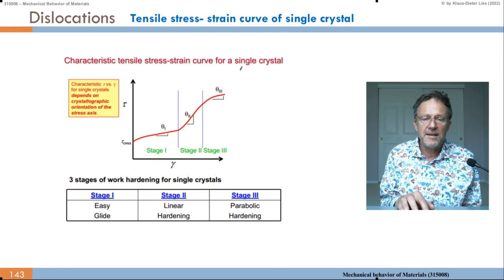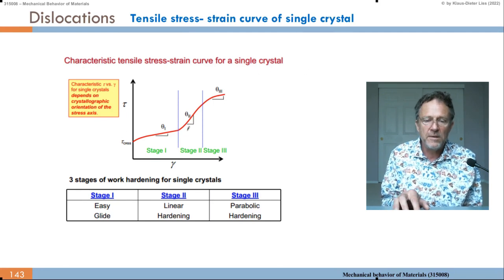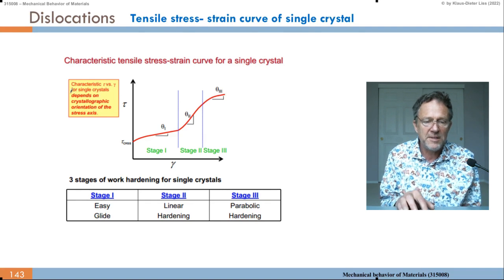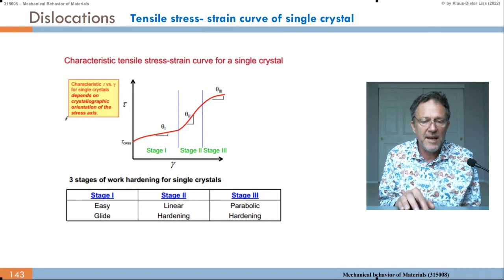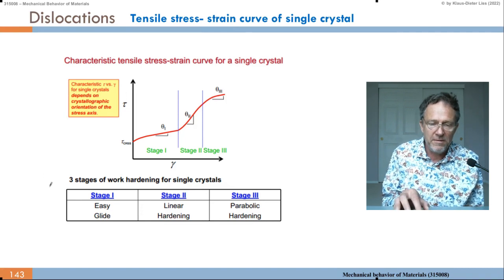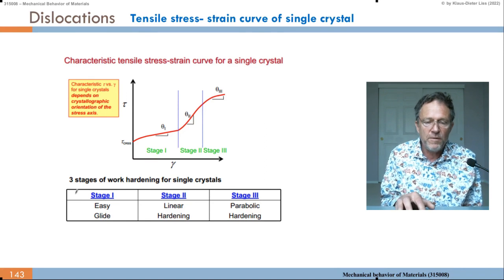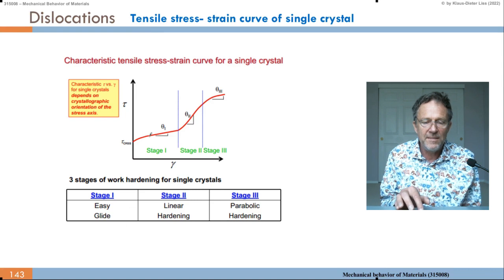So this is a characteristic tensile stress-strain curve for a single crystal. We have stage 1, then stage 2 with a larger slope, and stage 3 with a smaller slope. The characteristic tau versus gamma for a single crystal depends on the crystallographic orientation of the stress axis. Of course, we have had the Schmid factor. And there are 3 stages of work hardening for a single crystal. Stage 1 is easy glide. Then we have stage 2, linear hardening. Once we introduce dislocations, it costs some energy. That's why it's steep, but then it flattens. We introduce dislocations and they just move through the crystal and don't interact with each other.